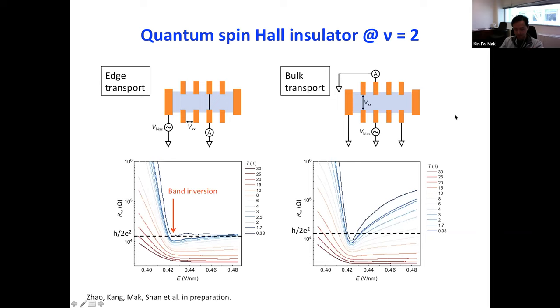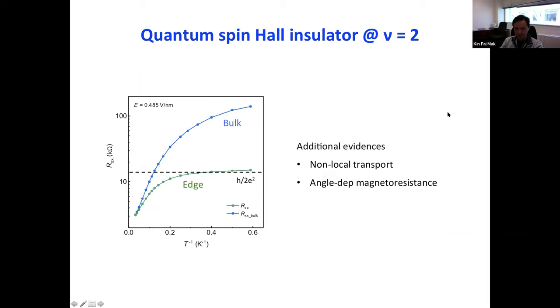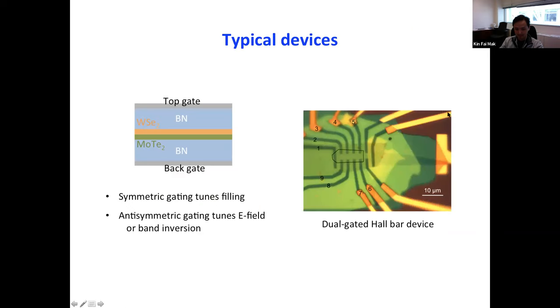We actually use a sort of contact gate to make the contacts better in our device. The contacts are made of very thin films, about 5 nanometer thick platinum electrodes. We use platinum because it has a very large work function, which matches well to this moiré system. There's also a particular reason we chose this combination of materials: first, the molybdenum telluride has a smaller band gap. Actually, it has the smallest gap among all the TMD semiconductors, which makes making contacts easier.